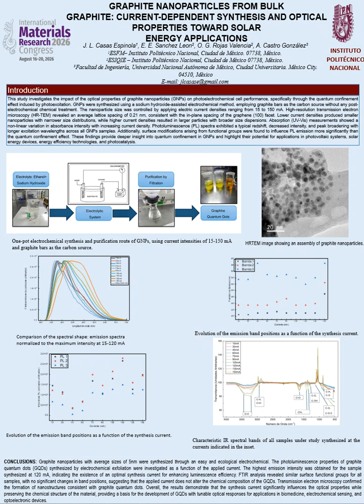Higher emission energies were observed for smaller GNPs, while lower emission energies were found for larger nanoparticles. In energy terms, the band gap gradually decreases as the size of the GNPs increases. This suggests that the PL emission originates from the quantum confinement effect, QC, occurring in the GNP's core, as is typically the case in semiconductor quantum dots, QDs. The carbon core is composed of a pi electron system, which could be strongly coupled with surface electronic states, thereby modifying the PL emission of the GNPs, Figure 3.